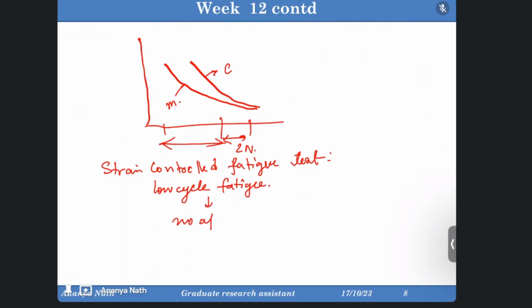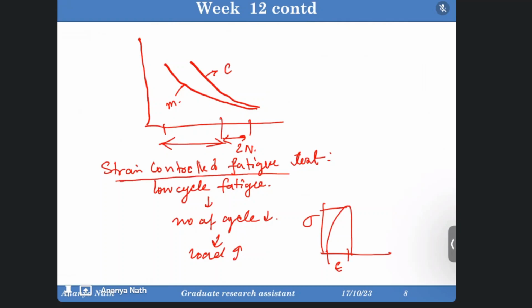So number of cycles to failure is less, means the load applied is very high, so there will be no space for the percentage elongation, and then the crack propagation, grain boundary detachment, those things will not take place. It will directly go up to the rupture point. So the graph will look like this. It will go to the rupture point. The strain will be very less compared to the stress. So as the strain is less, you can control the strength. So in that way you can remember that this low cycle fatigue test is the strain control fatigue test. There the composite will act like this.